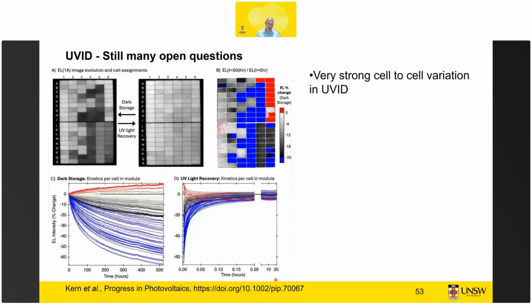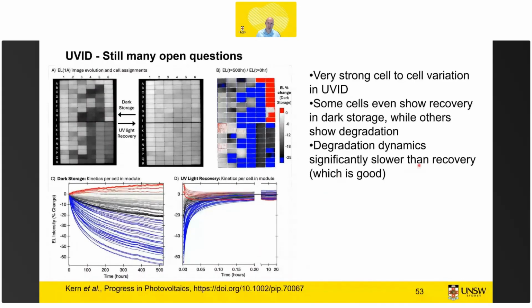You see that there's also this dynamics of degradation where even after 500 hours that cell is still degrading. And here we see that UV exposure brings them back to the starting point in 0.2 hours. So that's actually great news. The degradation dynamics are significantly slower than the recovery, which means your night is not 500 hours. Maybe at the Arctic Circle you will have dark periods that extend for that long, but normally it's, let's say, 12 hours on average. So you would be here. So not really a big issue. And whatever degradation you see, you quickly fix it.